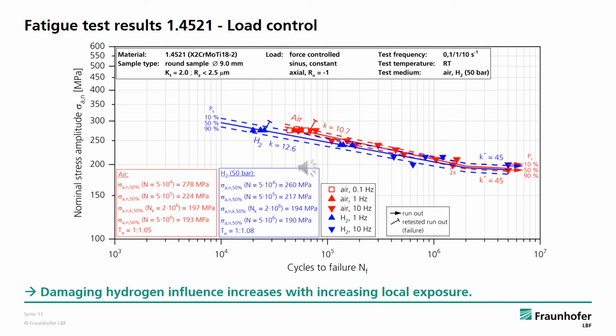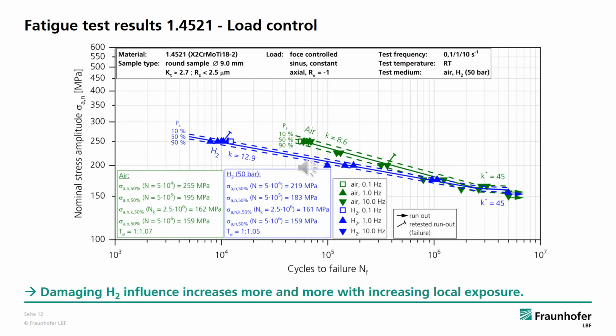This influence depends on the stress concentration and thus on the local stress. With increasing the stress concentration factor, the local stress also increases, which favors hydrogen absorption. The difference in fatigue life between air and hydrogen increases with the load. The greatest difference is observed with the SN curves of the sharply notched specimens shown here. The significant influence depends strongly on the local stress and is hardly visible anymore in the area of the knee point.